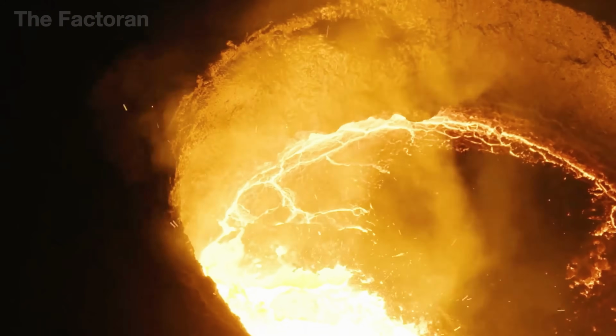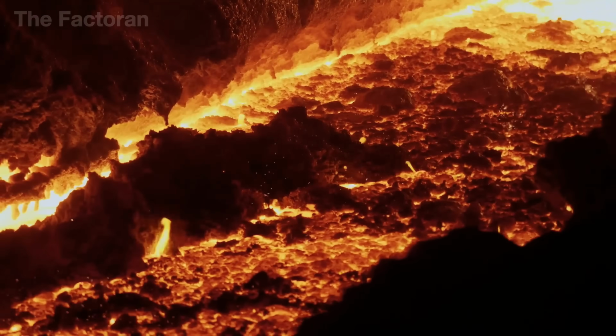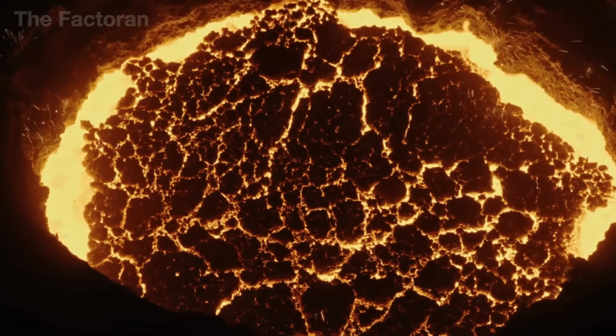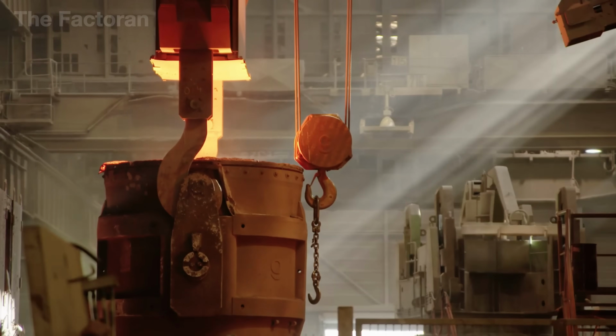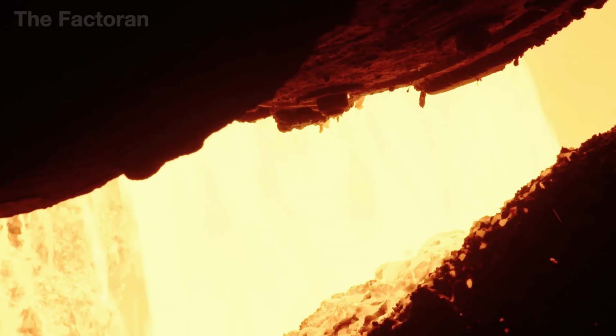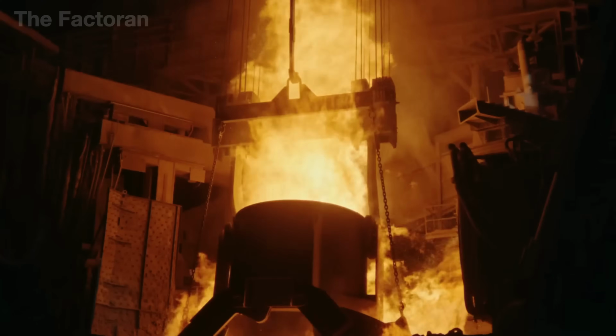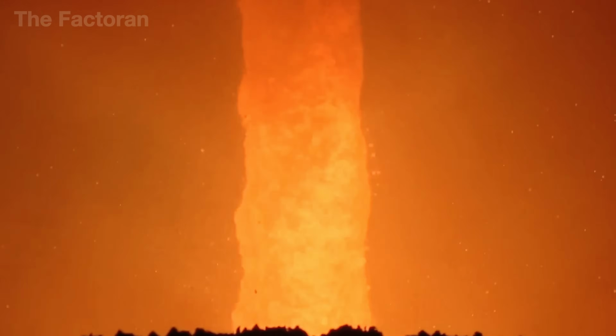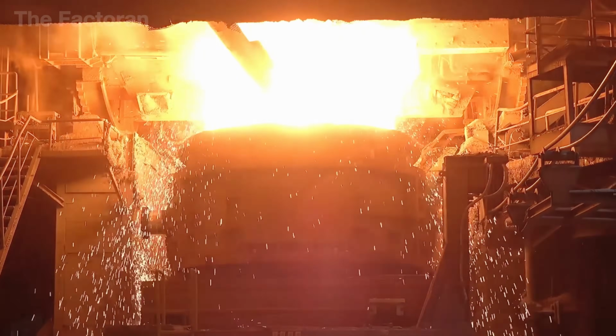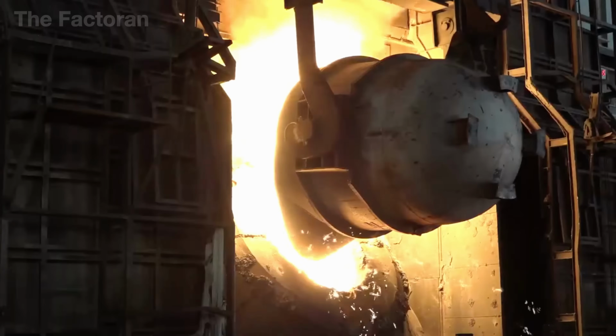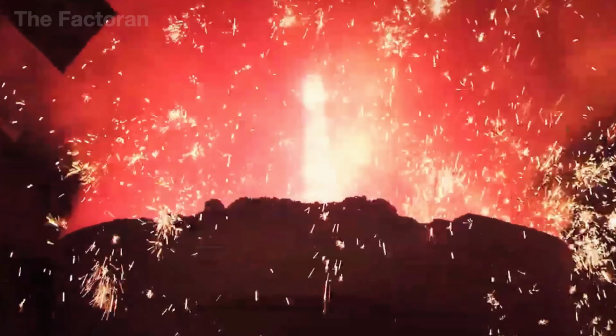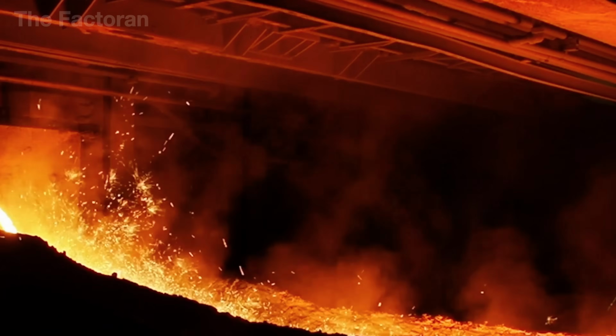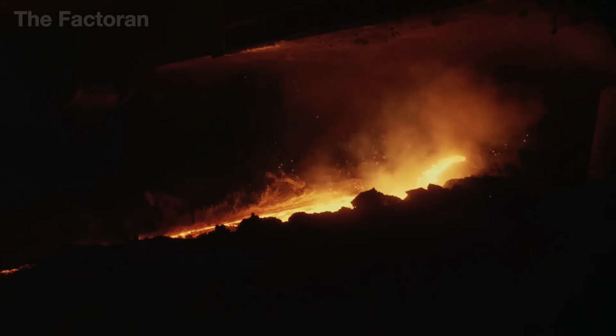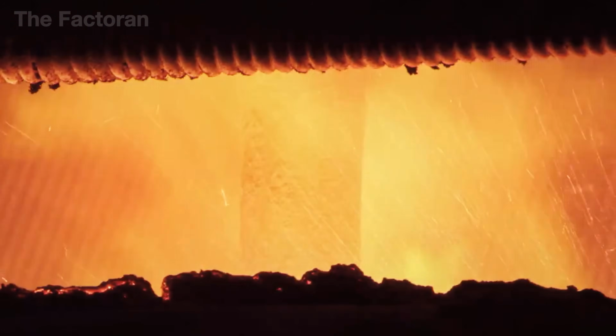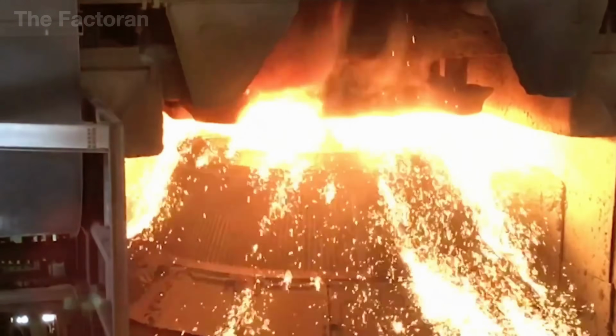Once it leaves the blast furnace, the molten iron, still blazing red-hot, is transferred straight into the basic oxygen furnace, a colossal steel vessel lined with refractory bricks. Here, the raw metal undergoes a violent purification. From above, a massive lance descends, blasting a jet of pure oxygen at tremendous speed onto the liquid surface. The oxygen ignites instantly, stripping away carbon and impurities, sending pillars of flame and bursts of smoke high from the furnace mouth. Amid the roar and blinding sparks, every fraction of carbon is burned off, transforming brittle pig iron into steel, cleaner, tougher, and infinitely more versatile. It is the very moment of rebirth when crude metal evolves into the foundation of human civilization.